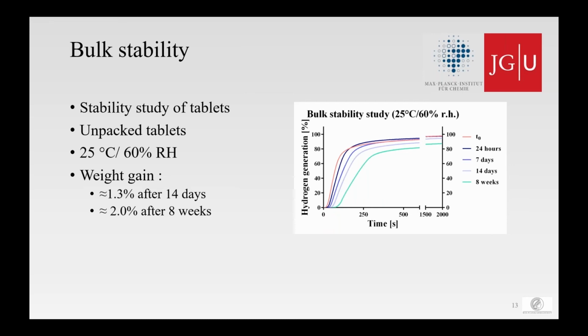There you can see small differences. So the initial non-stored samples, the T0 samples, show a quick and complete hydrogen generation. And over time, there is a decrease in the hydrogen generation speed and also in the amount of hydrogen that is generated. So after 8 weeks, it is significantly decreased in this case. So based on the DVS results, we gained important knowledge of our formulation, which enabled us to predict its stability during manufacturing and storage. So this was why DVS was very useful for this project.